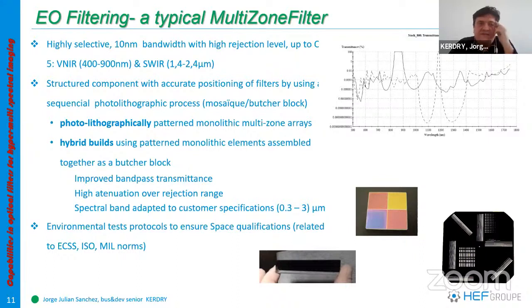One of our more innovative products is electro-optical filtering, multi-zone filters for space applications. We are about to launch highly selective filters whose bandwidth is in the range of 10 nanometers with high rejection level from near infrared up to almost 2.5 microns. We can treat in-house not only hybrid patterned monolithic elements, but also whole multi-zonal array photolithography, monolithic and hybrid. At the moment, promising results are conducting us to perform environmental tests to assure real space qualifications.